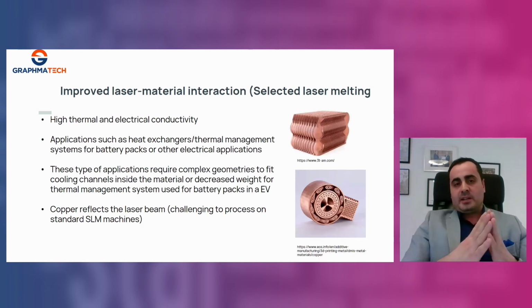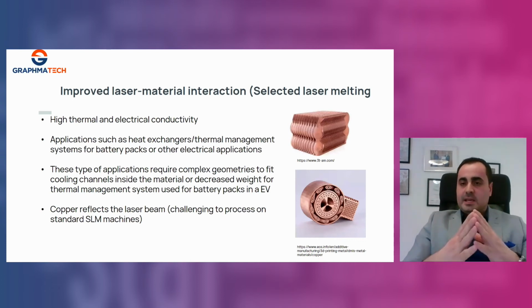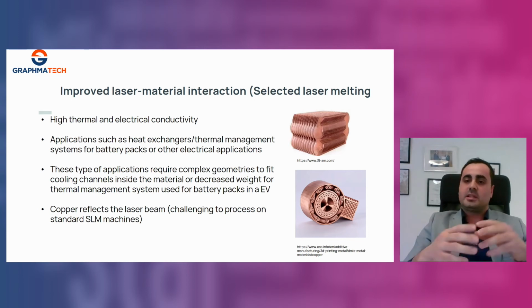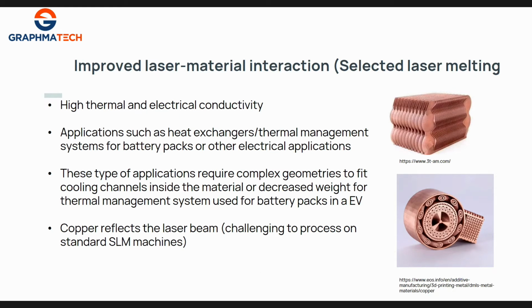So the other case, as I presented, is reflectivity, for example, in copper. Copper is an extremely interesting material for electrification. It's used mainly for heat dissipation and for connections and these kinds of things. And together with additive manufacturing, you add freedom in design to make it even more interesting. However, copper is proven to have a challenge in selected laser melting additive manufacturing technology. Because, as I said, it reflects the majority of the laser beam and you need really special machines with high power, green laser and these kinds of things. But what if we can make copper 3D printable basically on a wider range of selected laser machines?